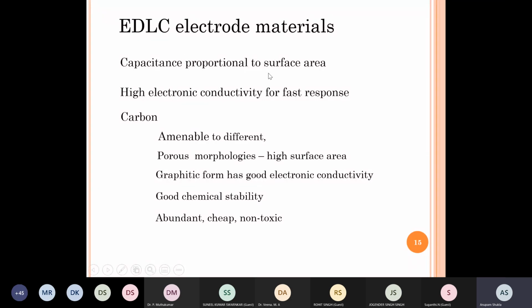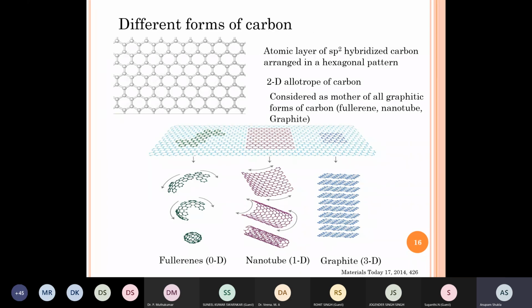Capacitance is proportional to surface area and requires high electronic conductivity for fast response. Apart from this, the material should also be chemically resistant to the electrolyte environment. And carbon actually provides all of these properties. It is amenable to different porous morphologies that provide higher surface area. If one goes to the graphitic form, that has good conductivity, good chemical stability, and is abundant, cheap, and non-toxic. So if you look at EDLC electrodes in the literature, most of them are carbon-based. And carbon comes in different forms.